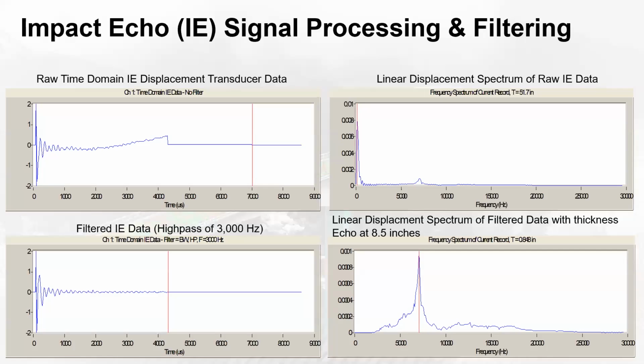So the basic signal processing in the raw time domain data is shown on the left, time versus voltage. And then with no filtering, you do the displacement spectrum of the raw data, and you see a resonant peak that corresponds to the transducer resonance and an echo peak that's weak right now at about 7,000 hertz. When it's filtered, you smooth out the signal in the time domain with a high pass filter of 3,000 hertz, and you get rid of that low frequency resonance that is just a function of the displacement transducer.